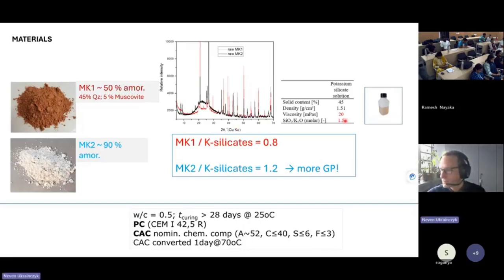Here you can see the viscosity, and the molar ratio of silicate to potassium is 1.5, but now we are using 1.7, because with 1.7 you can transport this. It's not hazardous, it's less alkaline, so you don't need special permission to transport this kind of silicates when you have the molar ratio of 1.7. That means less alkaline, more silicates. It also works very good. It's more sustainable.